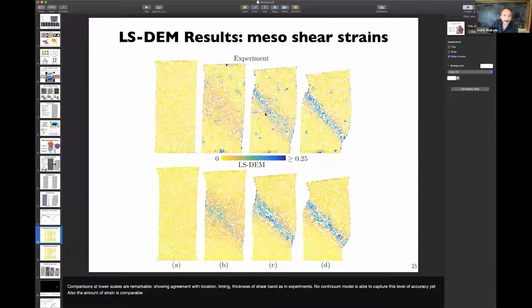So here is the mesoscale. On the top, you see the experiment. On the bottom, you see the computation, and you're hard pressed to tell the difference. The location of the shear band, the thickness of the shear band, the timing of the shear band, it's all predicted by the model. And notice that even the amount of strain inside of a shear band is matched by the model. And again, this is something that a continuum model would really struggle representing. Maybe it would get the direction of a shear band, the angle, but it would be almost impossible for a continuum model to detect the exact location of a shear band and definitely the strains inside of a band.